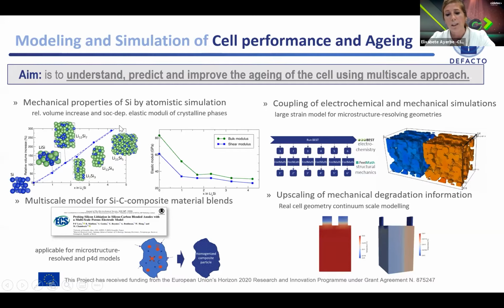Basically, we solve this with a multi-scale approach, coming from the atomistic scale, then going through the mesoscale, and then going up to the continuum scale. From the atomistic scale, we get more insight into the mechanical properties of the silicon, depending on the lithiation state. We've also been working on homogenization techniques for the silicon-carbon composite material. Our colleagues are also coupling electrochemical and mechanical models in order to properly track the impact of the mechanical aspects and stress on the electrochemical performance. And then we are running continuum-scale, large cell-scale models as well.